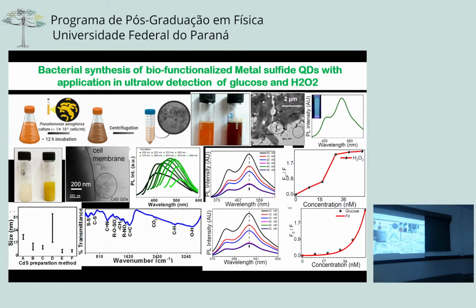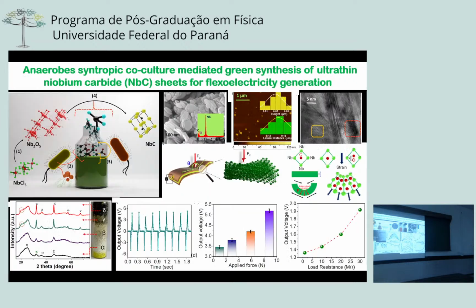We utilize it for biosensing; I'm not going to go into detail, but glucose, H2O2 sensing and so on can be done with this material. Also we can take this approach to make materials which are not possible under normal conditions. For example, niobium carbide: if you want to make it, you have to treat the material at 2000 degrees or above. We put in niobium chloride, it forms niobium oxide with the microbe, which can react and form niobium carbide of similar dimension with a defect which can be utilized for energy harvesting and so on.